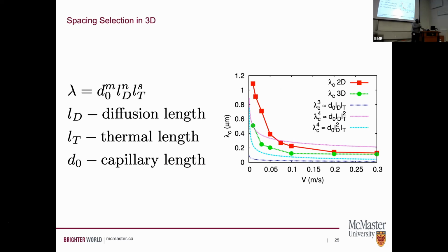In 3D, there are also theories, and most theories, at least with solidification, when you're worried about length scale, tell you that the length scale that results could always be assumed to be some sort of power law behavior between the length scales in your problem or in your system. In this case, the length scales are the diffusion length for both the concentration and the temperature, so the thermal length, and the capillary length. Those are the only length scales we have. And then the different exponents, depending on the theory you have, adjust to fit that.